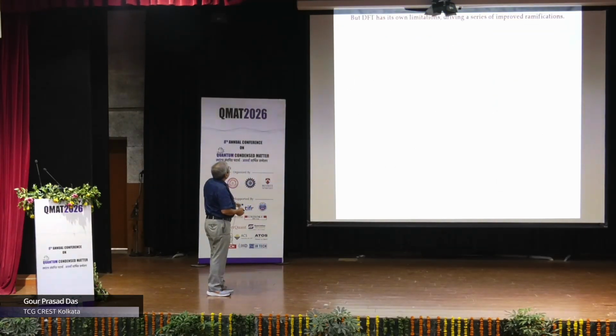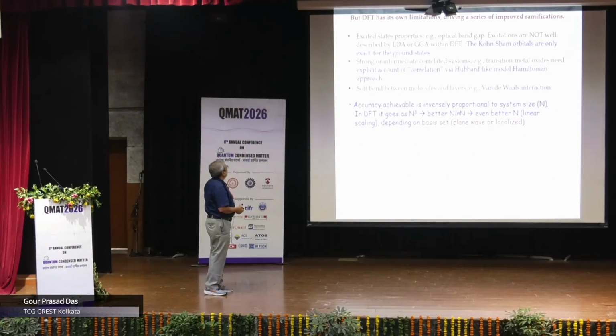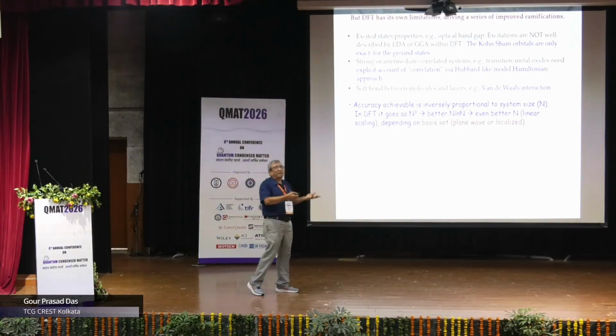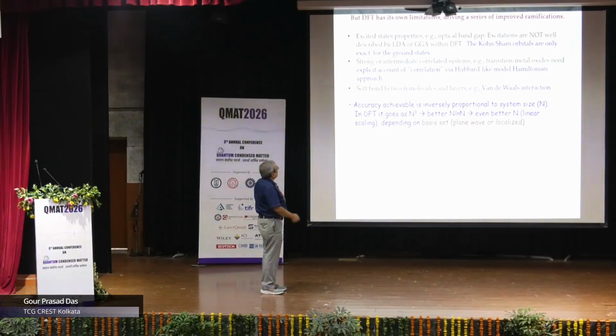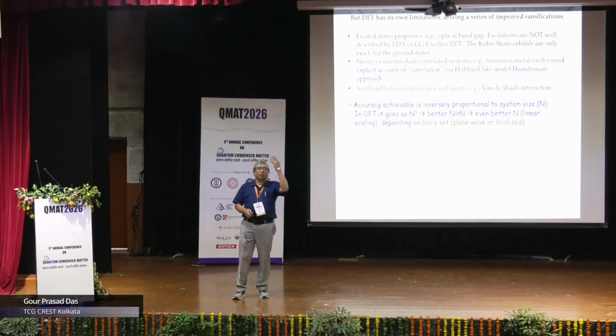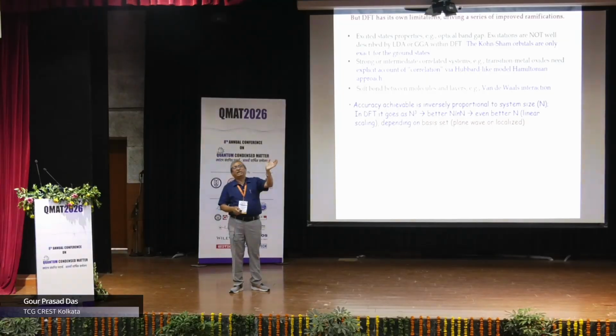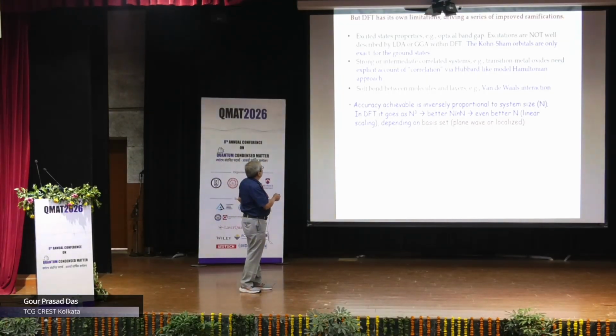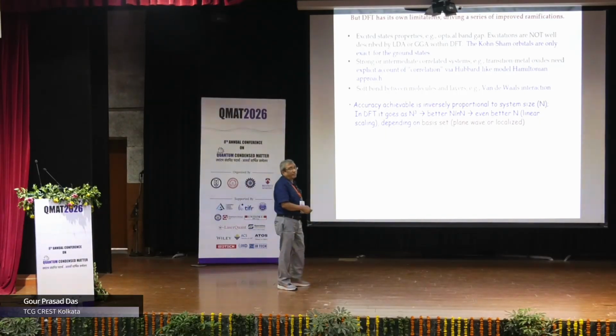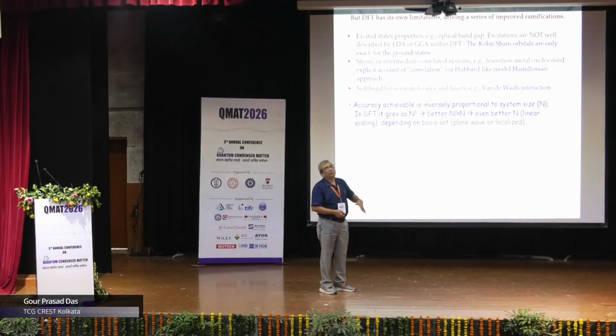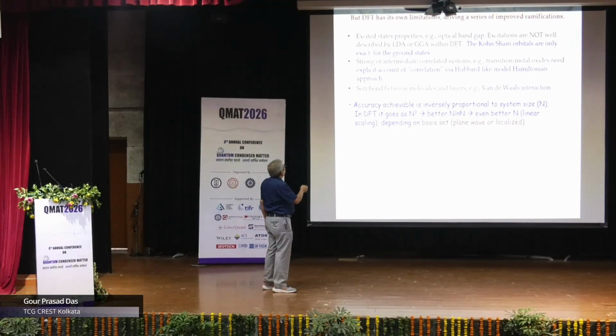Anyway, we know that DFT has its own limitations, driving a series of improved ramifications. And these are things which we all know. We know the limitations of DFT. For example, it does not give the band gap properly. The Kohn-Sham orbitals are only for the exact ground state, not for the excited state. We know that strongly or intermediately correlated systems such as transition metal oxides need explicit account of correlation via Hubbard U. Most of the students routinely use in their simulations LDA+U or GGA+U. That U is nothing but the Hubbard U in the model Hamiltonian approach. And for example, van der Waals interaction is something which per se is not included in DFT, so we introduce what is known as the dispersion correction. There are many such limitations of DFT, but we also know how to overcome them. So the accuracy achievable in a DFT calculation is inversely proportional to the system size, which is N.